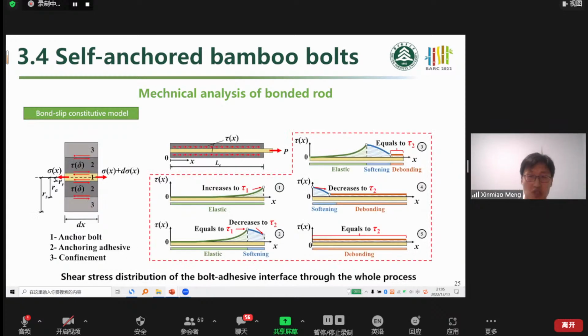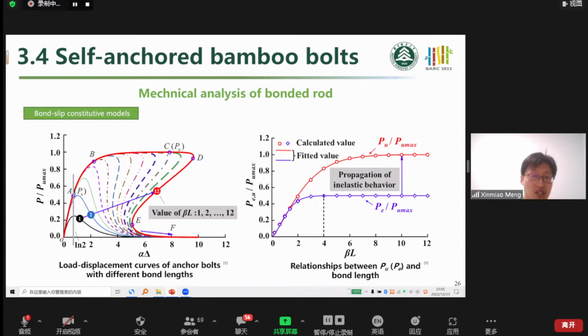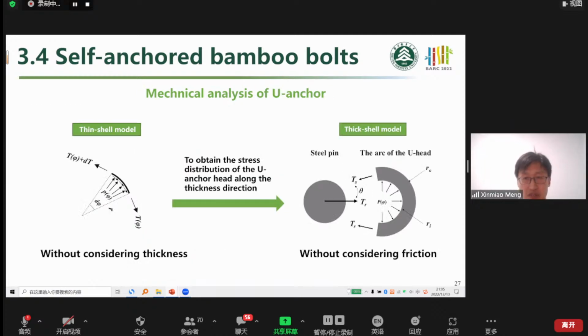And here is the trilinear model. We obtained the shear stress distribution at the interface through the whole loading process. And then we studied the relationship between the load carrying capacity and the bond length. And we found that we need to optimize the plastic performance to improve the capacity. As for the U-shaped anchor, we combined the thin shell model and the thick shell model to get the load distribution and the stress distribution across the section.